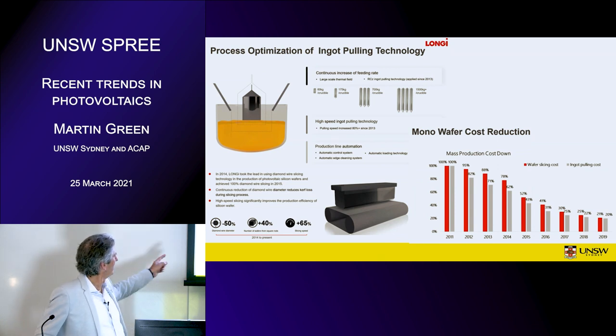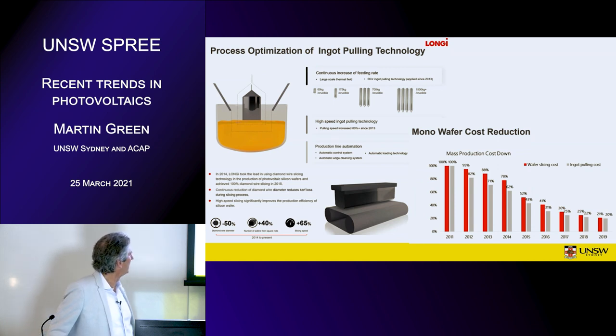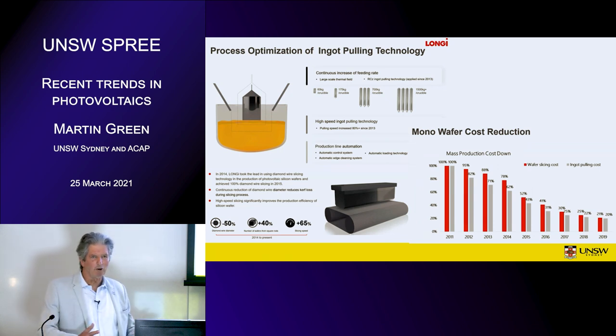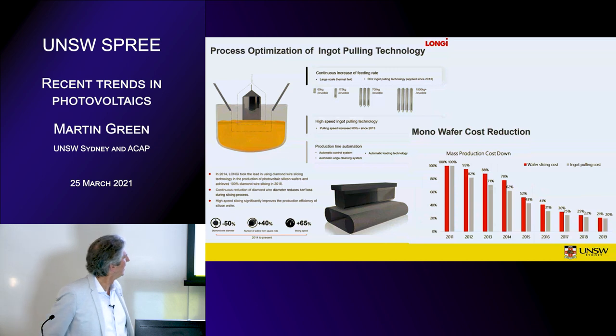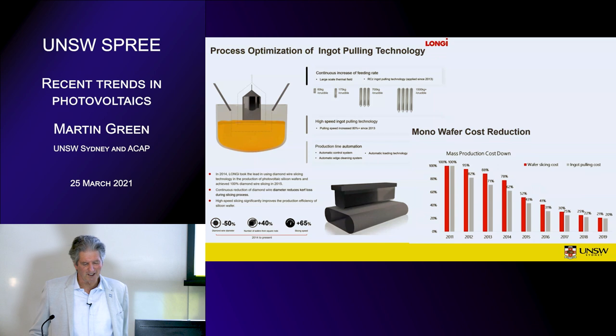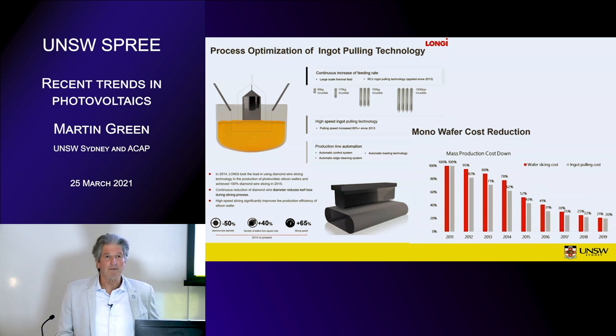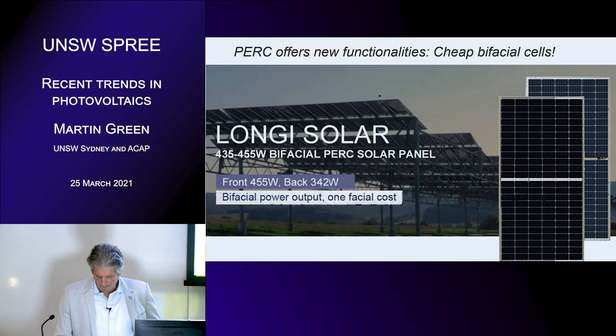So the wires have got thinner by 50%. The kerf loss has reduced, so you're getting 40% more wafers per unit length. And the cutting speed has gone up 65%. So, massive improvements in the sawing. So that's been part of the reason that PERC has done so well.